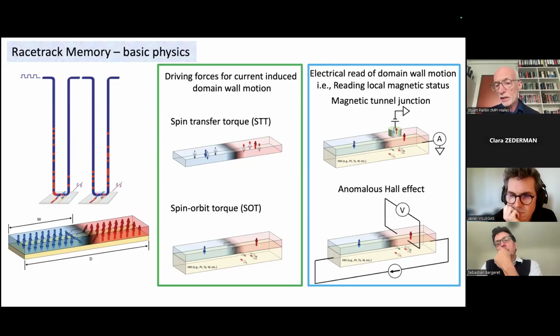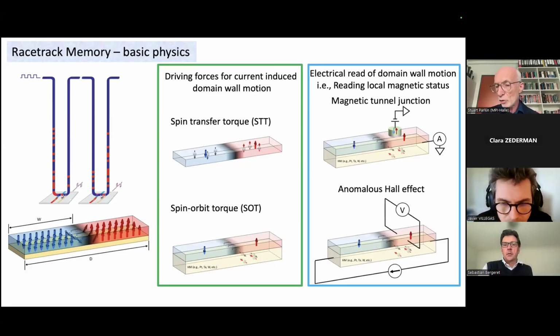On the other hand, shown below is a different way of measuring the domain structure using the anomalous Hall effect. So there are a lot of Hall effects, as you're all very familiar. In this case, in a magnetic material, a ferromagnetic material or ferrimagnetic material, the charge current is converted to a transverse spin polarized voltage, which is the anomalous Hall signal. And that enables us to detect very tiny racetrack technologies.